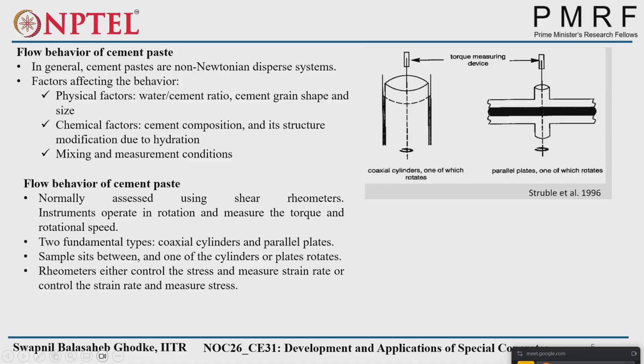This is the parallel plate rheometer, two plates above each other, and there is a gap between. If we have too much flowable material, the material will not be able to stay between the plates. So a little bit stiff material we can have between the parallel plates. Whatever stiff material, if you want to measure the rheological properties, we can use the parallel plate. And for too much flowable material, we can use the cylinder type or coaxial type of rheometer.